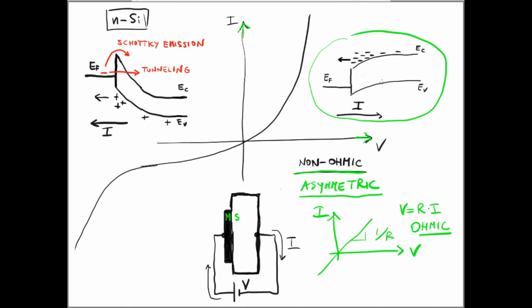So the more we increase the voltage, the more electrons will be able to populate the conduction band of the material in the region close to the interface. Remember that the Fermi energy is like that. So the more we increase the voltage, the more the Fermi energy crosses above the conduction band, at least very close to the interface. And so this means that all these states below the Fermi level are heavily populated, and so the current increases effectively exponentially now. And that's why it has this behavior here.